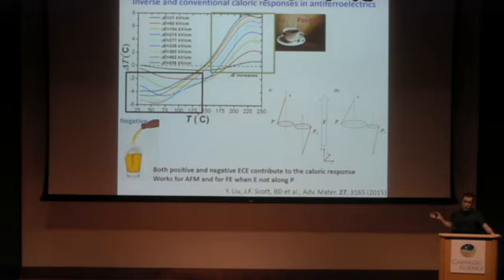And actually, you can exactly apply the same kind of story. It works very well for antiferroelectrics. And as has been described by Andrew just before, of course, if you have the polarization that way and you apply an electric field in that direction, you will force the disorder to increase in your system. This is what has been described just before, which is very nice. From modeling point of view, this is for kids, you know.